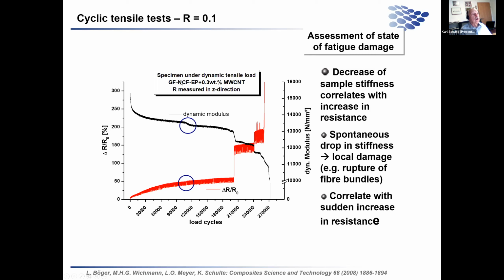Here again, the glass fiber composite with 0.3% multi-wall carbon nanotubes in the matrix. It is electrically conductive, and we have plotted here the resistivity increase versus the number of load cycles, as well as the dynamic modulus, meaning the degradation and decrease of the material's modulus. Once there is a decrease in the modulus, there is damage occurring, and that damage can be seen in the resistance change. In case there is stronger damage in the matrix, you immediately see a jump in the electrical resistivity. So the electrical current capability of the matrix can be used to sense damage, respectively strain.